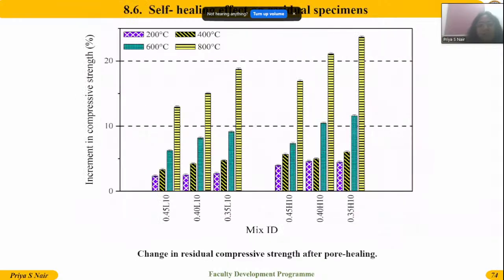Okay. Then the increment in compressive strength. When I took some samples after this temperature, some cracks were made over the surface. I placed some selected samples in the water to check the self healing, and I noticed that after the temperature, when I placed the sample in the water, the sample healed effectively, and the healing percentage, the strength percentage, varied. Around 24% increment in compressive strength was noticed after the temperature.